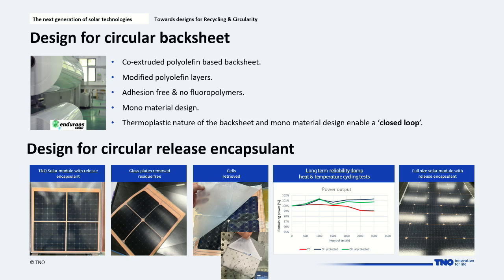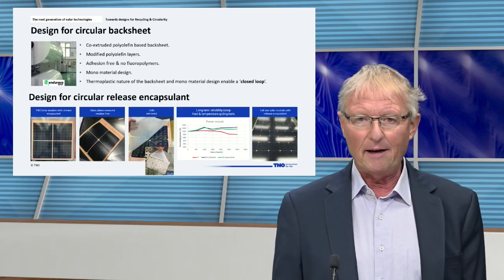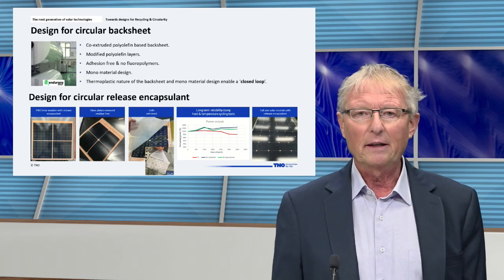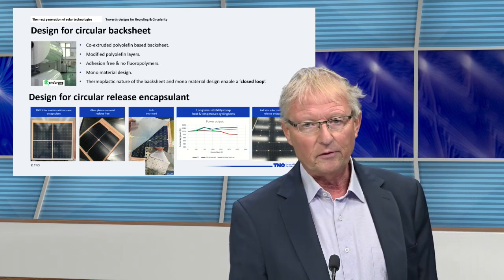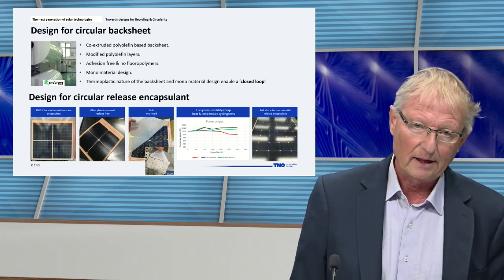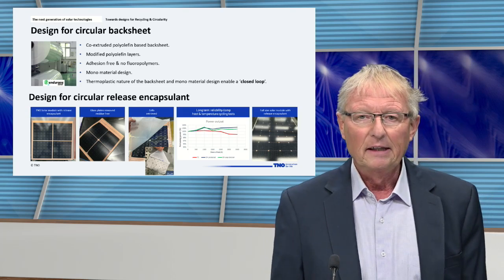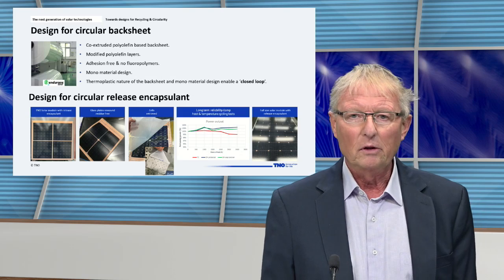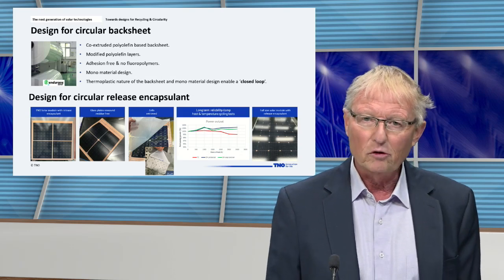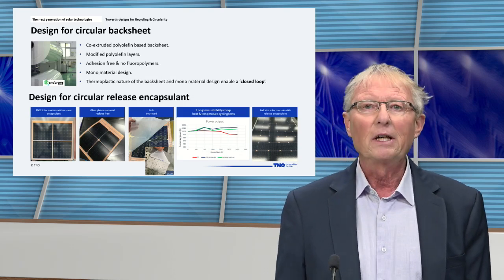And these modules have been thoroughly tested for long time reliability following the IEC 61215 protocol, damp heat and temperature cycling. The tests were prolonged 3 times instead of the required 1 time, which is 1,000 hours of damp heat and 200 cycles of temperature cycling. The experiments now go all the way up to full-size 60-cell modules comprising this release encapsulant.